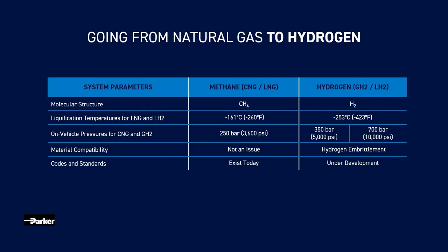With regards to the material compatibility, for methane, there are no issues. However, when we're dealing with hydrogen, and because of the extremely small molecule size, there is such a thing as hydrogen embrittlement, and we'll be discussing that further in the presentation. And then finally, the codes and standards. Because methane has been in the industry for over 20 years, those exist today, whereas the hydrogen codes and standards are currently still, in some cases, under development.